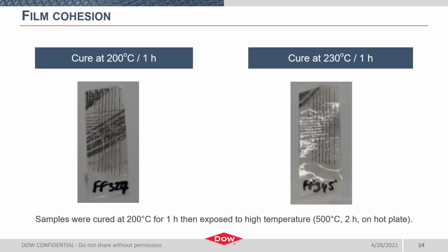The level of film cohesion was also assessed based on the amount of material removed with Scotch tape during the adhesion test. Since this adhesion test on the substrate rated 5B, or nearly perfect, we were able to visually assess the amount of cohesion by material on the tape. Had we had a less than perfect adhesion rating, we may have worried that the material on the tape was adhesion failure, but this wasn't the case. So we were able to look at cohesion this way.